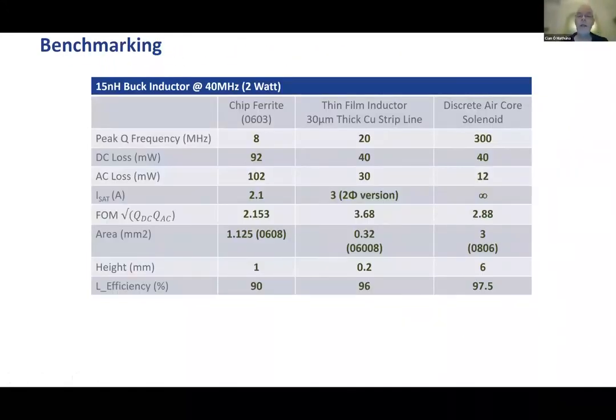But the most important thing as well is if you look here at the footprint area of the different inductors: the ferrite, over 1 millimeter square, the air core over 3 millimeter square. Whereas here with the thin film, we can be as small as 0.3 millimeter square. Then if you look at the height of the inductor, the ferrite is 1 millimeter, the discrete air core is 6 millimeter in height, and the thin film inductor is only 0.2 millimeter in height. So this is where the magic comes in.